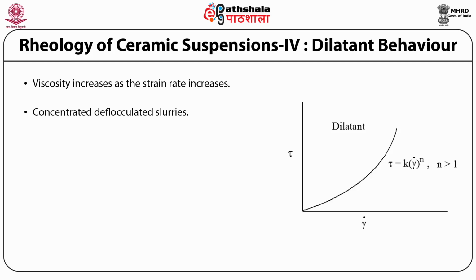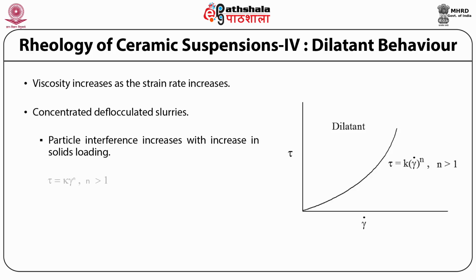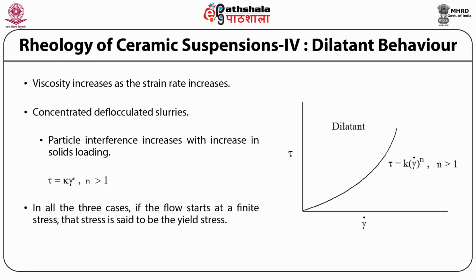With increasing strain rate, the particle interference increases, leading to an increase in the viscosity. This behavior can also be described by the power law, which we have mentioned earlier, that tau is equal to k into gamma dot to the power n with n greater than 1. In all the cases which we have mentioned earlier, sometimes the plot does not start at the origin but starts at a finite value of the shear stress.